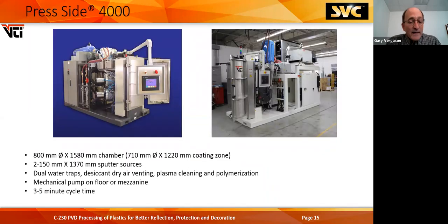Machines keep getting bigger. Parts got bigger. They got more complex. They're wrapped. Some of these parts are 20 some inches long, and they're a foot deep. So the chamber had to increase in size. We added water traps to help pump water vapor out of the system. This blue tank is a clean tank that stores a desiccant dried air that we power vent the system back. So the system comes back from vacuum to atmosphere in about 9 seconds.